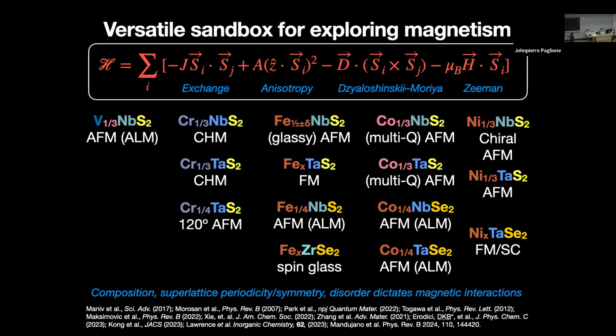So for example, the vanadium-intercalated niobium system is a candidate altermagnet. The chromium 1/3 niobium and tantalum sulfides have been known since the 70s or 80s to be chiral helimagnets, by groups in Japan, Togawa's group and others. My group has recently put on arXiv a paper about chromium 1/4, which is a 120-degree non-collinear AFM. I'll tell you a little about that today. And then this is Ephraim's material, cobalt 1/4 tantalum selenide, also another candidate altermagnet, and so on. So there's tons of stuff that you can do here.